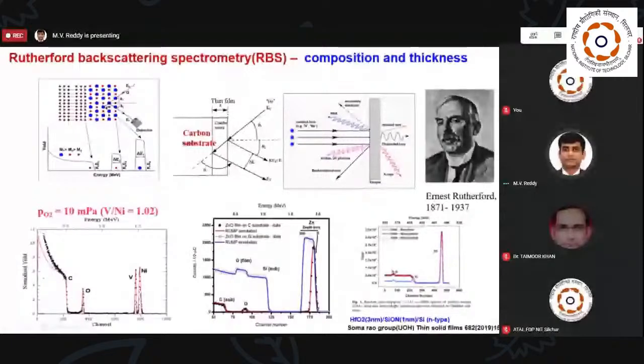For example, if people are working with CMOS, they call it hafnium oxide 3 nanometer and silicon oxide 1 nanometer on a silicon substrate. I think this is the only technique, the best technique, to get high resolution, good information about the composition. You can see the hafnium. So for the expected composition, we can do simulation by using RUMP, or different options are there.